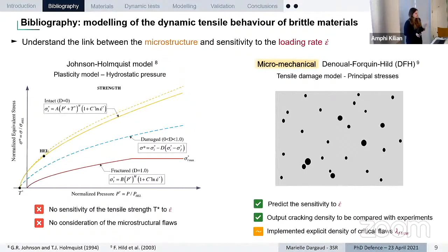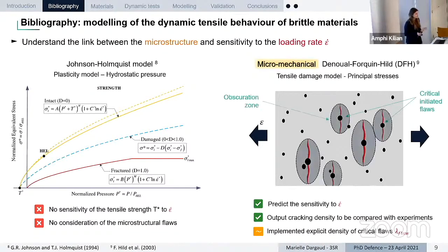Here in this material, we take into account a random distribution of flaws in the material. When we apply a tensile loading, we increase the stress in the material, and when it overcomes the failure stress of one defect, some cracks are going to trigger from these defects, and these cracks are going to induce a local release of stress, which can be represented by this obscuration zone, and any other pore